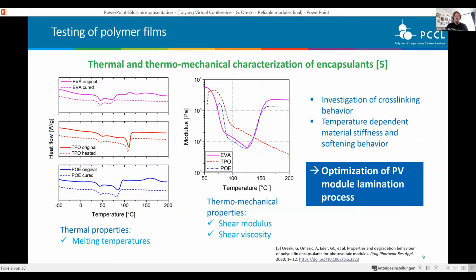So some examples of where testing of polymer films is actually quite useful. For example, when you do a thermal and thermomechanical characterization of the encapsulants. So what do you learn there? You see where my melting temperatures are. You see something about the cross-linking of the material. When you do thermomechanical properties testing, you can learn something about shear modulus and shear viscosity. So parameters that are important for a PV module lamination process.